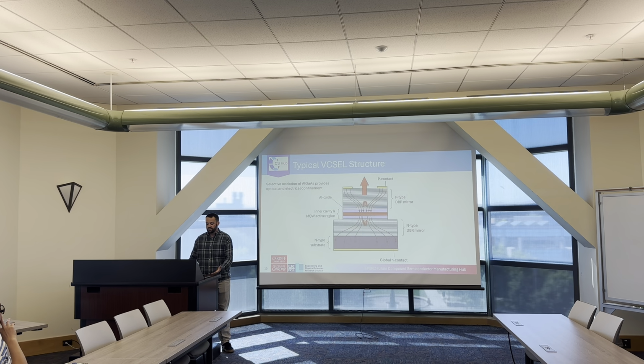So before talking about a VCSEL, I just wanted to talk about a typical VCSEL. So we have a multiple quantum well active region sandwiched between distributed Bragg reflector mirrors, which are doped, with a high aluminium content layer in the top Bragg mirror, which after selective oxidation provides optical and electrical confinement, usually grown on an N-doped substrate, and then you can make a P-contact metal and N-contact metal on either side of the VCSEL.